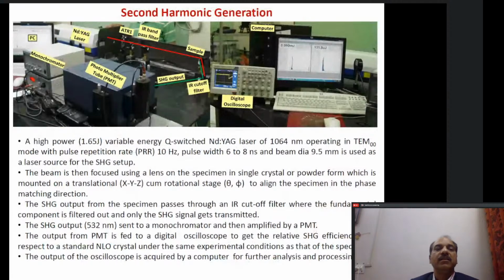Similarly, we have a second harmonic generation experiment in our laboratory, in our division, which was used for finding out the efficiency of some of the crystals which we have grown. A high power Q-switched Nd:YAG laser of 1064 nanometer is used, operating in TEM00 mode with a pulse repetition rate of 10 Hz, pulse width of 6 to 8 nanoseconds, and beam diameter of 9.5 mm. The procedure is that first the beam is focused using a lens on the specimen, in single crystal or powder form. You can do powder SHG or single crystal SHG, mounted on a goniometer having XYZ and R, theta, phi degrees of freedom to align the sample in the phase matching direction.